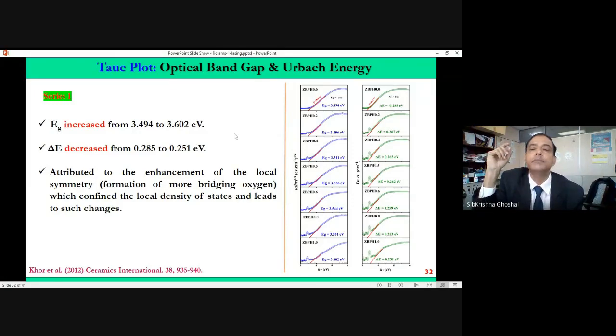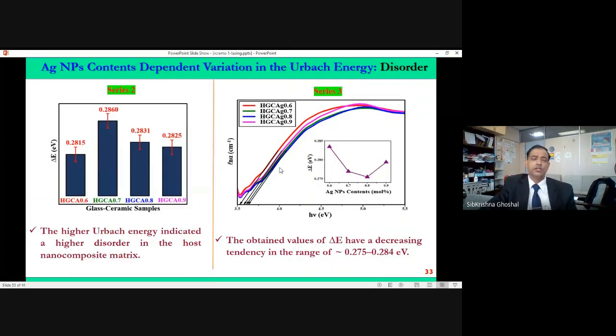And that's where glass ceramics are interesting, because you can tune the band gap over a wide region by controlling the concentration of the nanoparticles and combinations. And you can put two different nanoparticles, three different nanoparticles, two different rare earths, three different rare earths, depending on your aim. So that's the way we are trying to do. When you put the silver nanoparticle, in the presence of silver nanoparticle, the disorder changes. That's exactly what I was talking about. Local symmetry of the system changes. This local symmetry will control the optical properties. And that's where Judd-Ofelt theory comes in. We also do Judd-Ofelt theory to compare with the results.